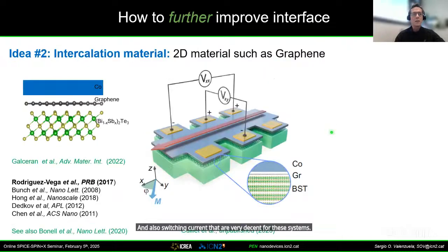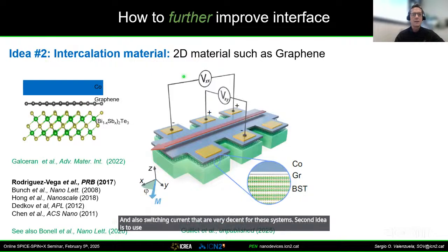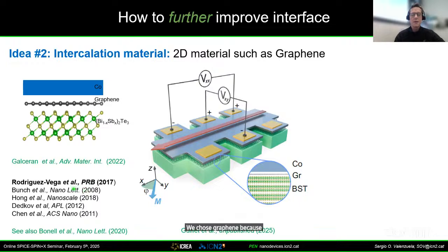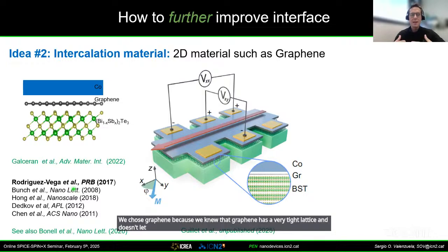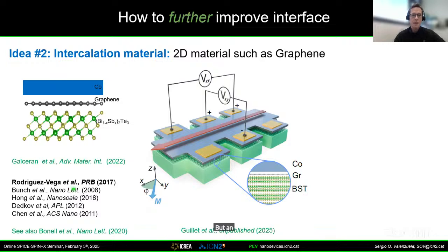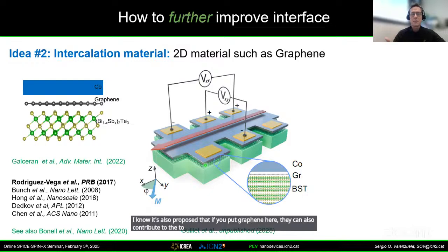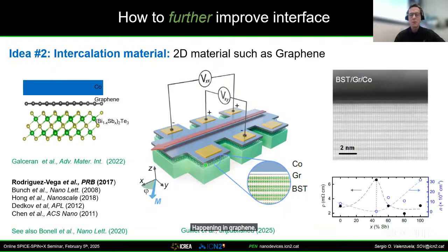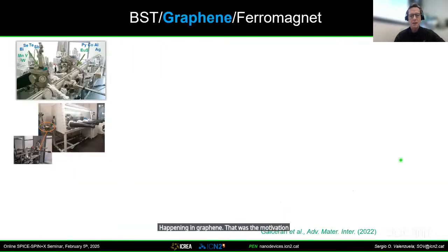Second idea is to use an intercalation material that could be graphene. We chose graphene because we knew that graphene has a very tight lattice and doesn't let any material go through. Even helium can be trapped, and hydrogen can be trapped by graphene. And this was known a few years back. And it was also proposed that if you put graphene here, they can also contribute to the spin torque because of Rashba-Edelstein effect happening in graphene. Well, that was the motivation. We obtained very nice heterostructures.